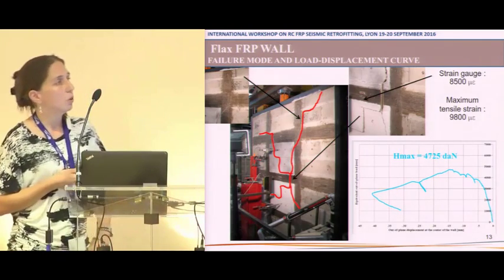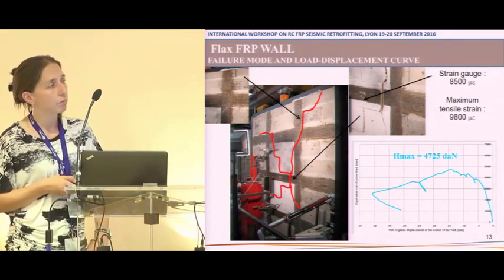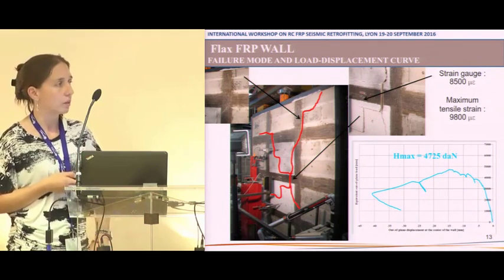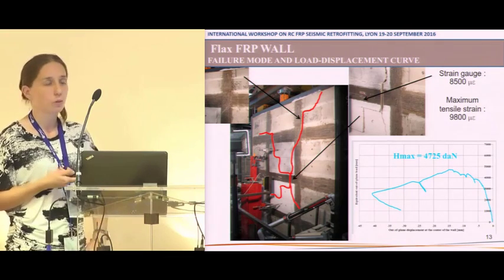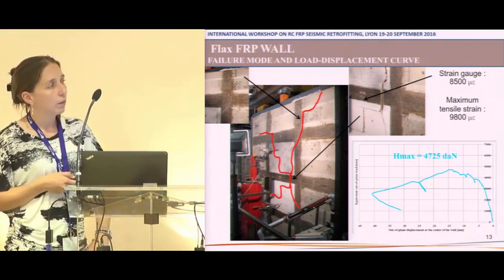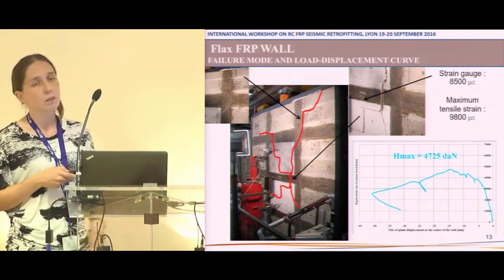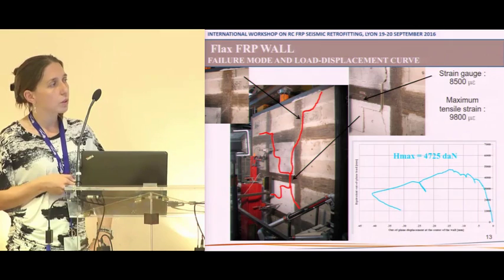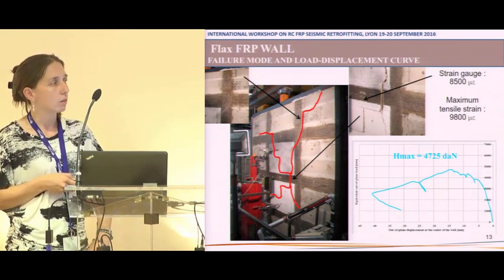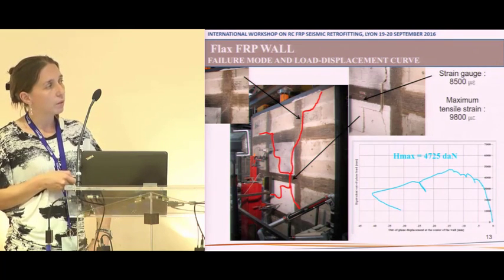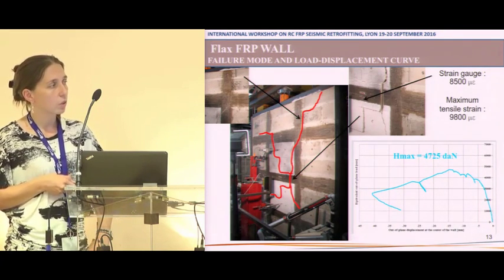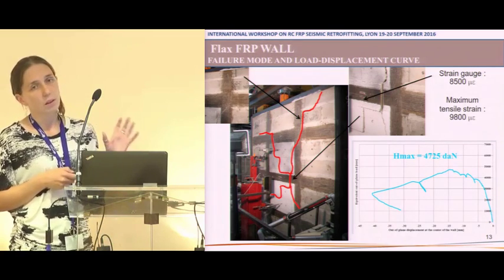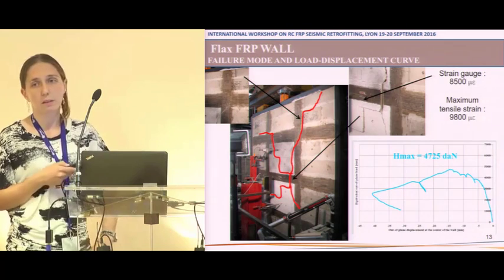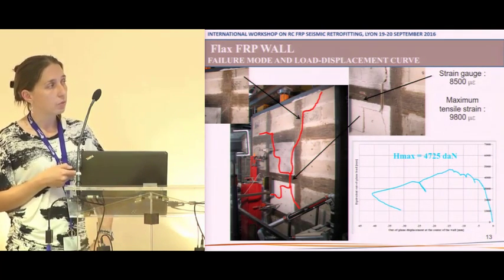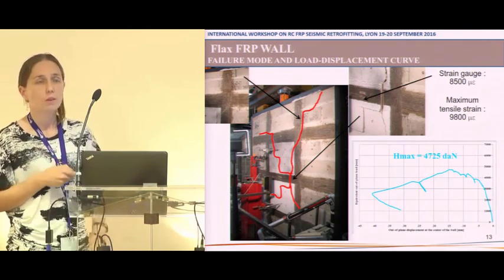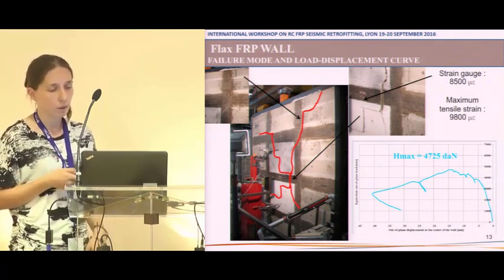Concerning the wall reinforced with FRP, we can see that the first phase is larger than in the previous case. So the FRP delays the first macroscopic damage, and the crack pattern is rather similar to the previous one. We have a vertical crack with a slight deflection here, and inclined cracks directed toward the corners. It seems that FRP does not deviate the cracks that are formed. They only contain the cracks and control their opening.